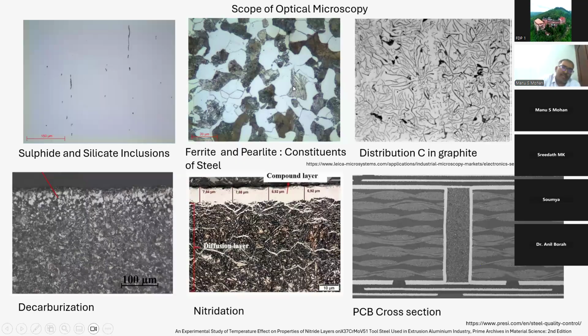Another thing we have here is the microstructure of the carbon steel. You can see the ferrite and the pearlite phase. Ferrite means it's a BCC structure, and pearlite means it consists of alternate layers of ferrite and cementite. That is why you can see the dark and white lines here.